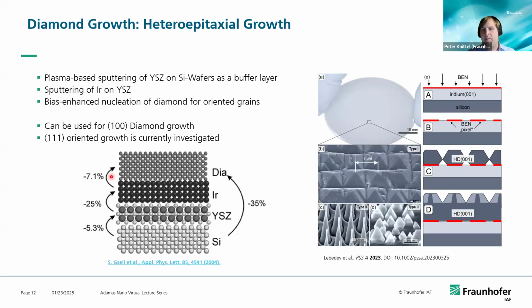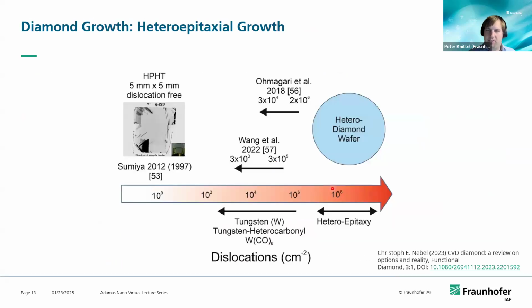And you may ask, if this is already possible, producing diamond wafers, why don't people use diamond wafers all the time? First off, you don't get them easily at the moment in this large size. You get small pieces, but the bigger drawback is actually, so this is just an image of a 2-inch wafer that we also have at IF. The problem that we see at the moment is that these heteroepitaxial diamond wafers have very high dislocation densities, up to 10^8 per square centimeter.